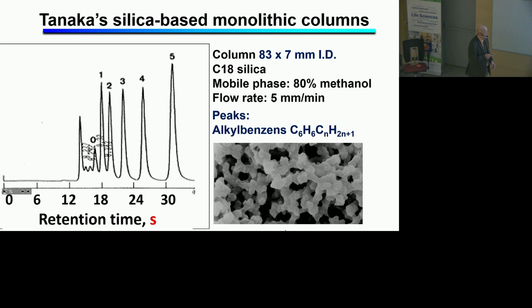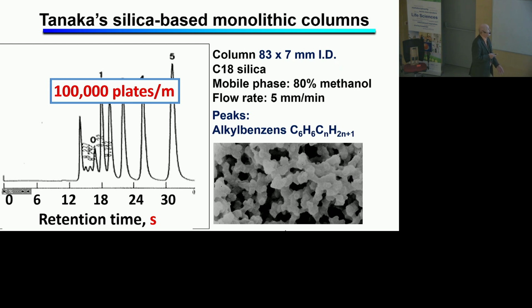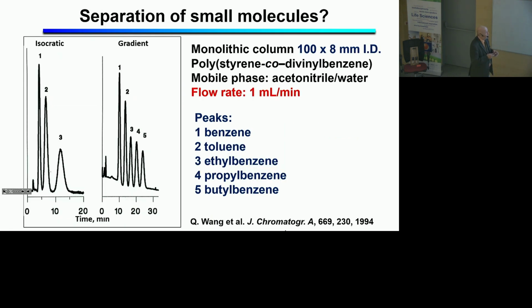We can control the porous properties as well, simply because, as I said, the separation using silica-based monolith is a little bit different, simply because the structure is different. As you see, Nobuo Tanaka separated 5 alkyl benzenes in about 30 plus seconds in 1996 and received about 100,000 plates per meter. If we used a similar approach, made our monolith and tried to use this for separation of alkyl benzenes, we needed about, in the best scenario, 15 minutes, in the worst scenario, about 30, which is completely useless, and the separation efficiency, 13,000 plates, is completely useless.